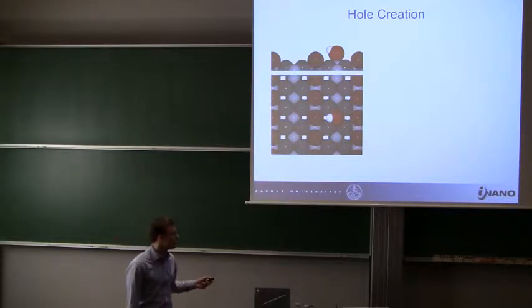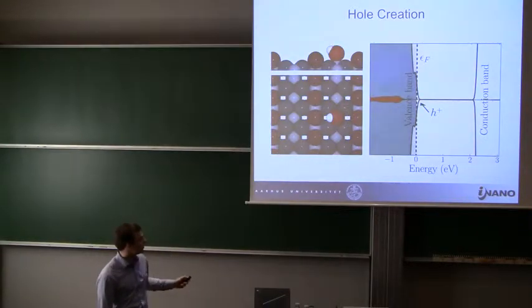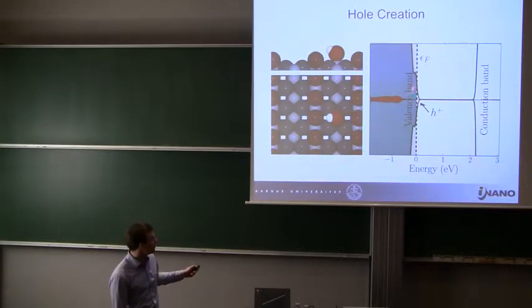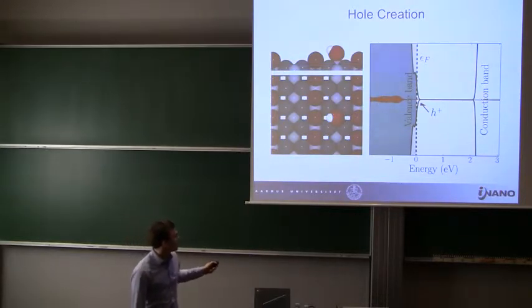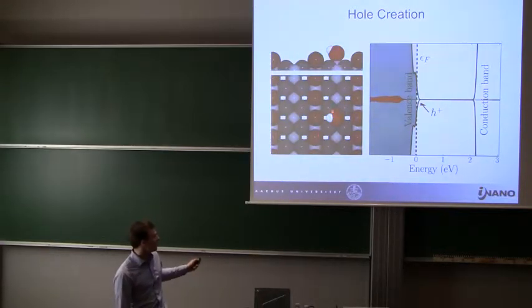We have the 110 surface, which is the most studied surface of the rutile TiO2, with titanium trough going here and bridging oxygen here. Now we have put in one OH group in the titanium trough, and we see from the density of states that this actually creates a hole in the top of the valence band. We can also see from the projected DOS onto the OH group that the hole is much centered on the crystal rather than at the OH group.